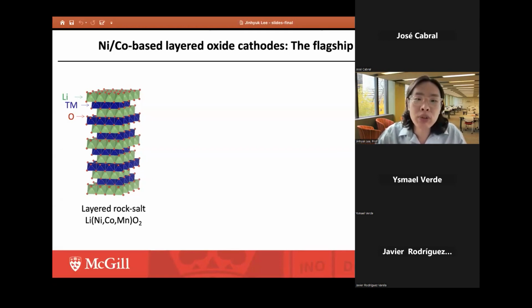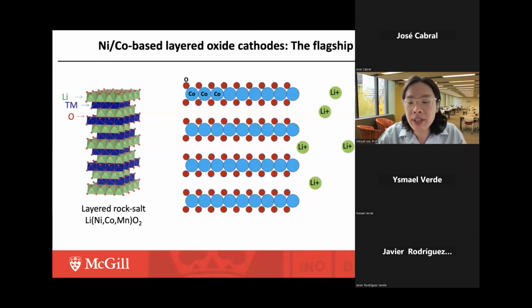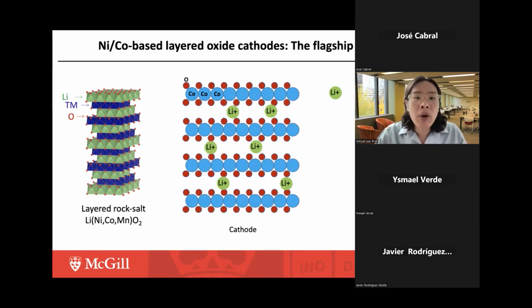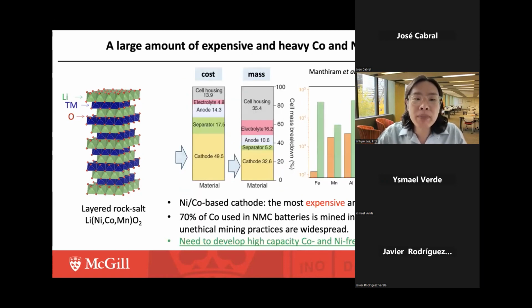Now, this material could deliver very high capacity owing to this 2D lithium diffusion pathway in the lithium plane and a two-dimensional transition metal plane, such that the lithium ions can easily go in and out of the cathode structure along with the electron conduction. But unfortunately, these materials are typically made of a large amount of expensive and heavy cobalt and nickel, which makes the cathode the most expensive and heaviest component in the lithium-ion battery.